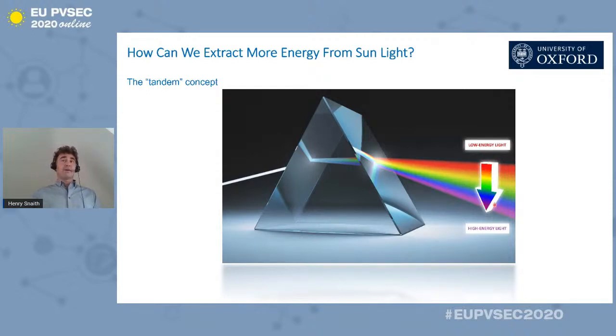But very briefly, the main idea for anyone who wasn't watching that or isn't aware is that the solar spectrum comes in a range of colors, and these colors carry different energies, going from about 3.5, 4 electron volts right in the UV part of the spectrum down to around 2 electron volts in the red, and then dropping down further into the infrared. All this extra energy or voltage is lost if you absorb it in a single junction solar cell. It's lost as heat, thermalization. So the blue photons at 3 eV, if you collect them in a 1 eV gap solar cell, you're throwing away 2/3 of the energy straight away.